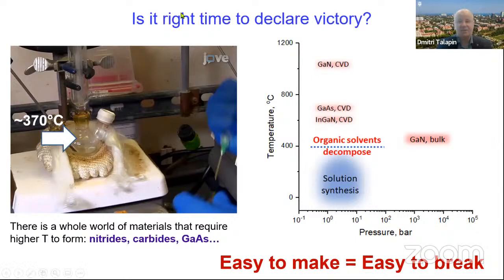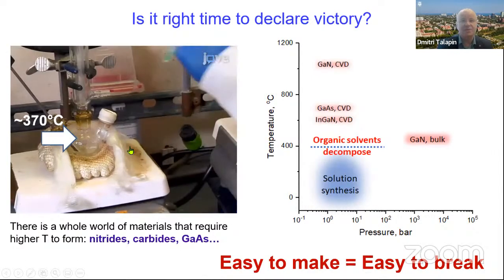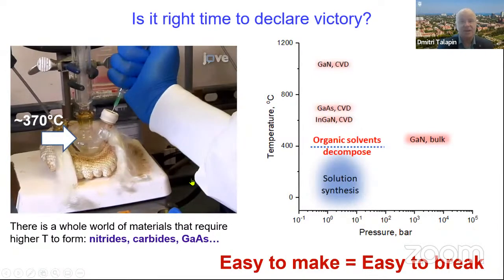The problem is that you probably remember that video I was showing you, a video of synthesis, and that time I didn't give you full detail. This flask was preheated to 370 degrees Celsius. He had the solution preheated to 370 degrees Celsius, and this is very close to the highest temperature that we can achieve before the solvent starts falling apart. It's close to the highest temperature achievable reliably for organic solvents.